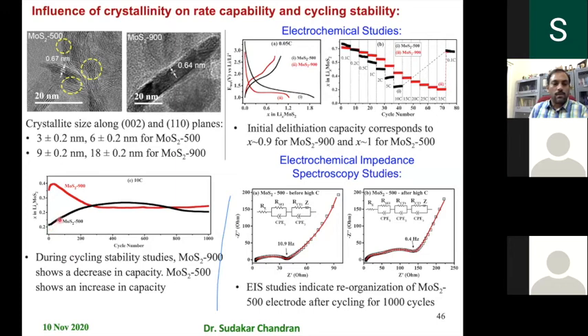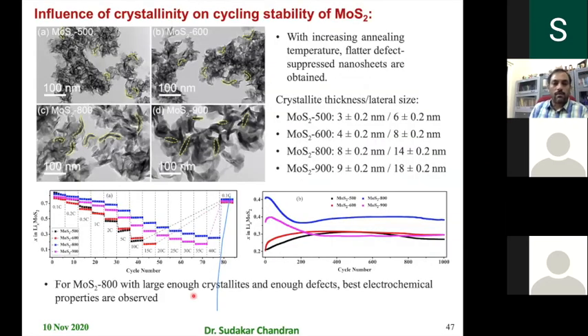So we see that whenever you have defects, initially the intake keeps on increasing. So the defect is doing something to the structure, it makes it take more and more lithium to begin with. Whereas in the highly crystalline defect-suppressed nanosheet, it doesn't allow the lithium to be taken in. Of course, very little lithium is taken into the system in the first place in the defect-rich nanosheets. This tells us that after about 500 cycles, both systems converge to more or less similar structural features. So this is something one should explore. That's where we are looking at what structural changes are happening and so on.